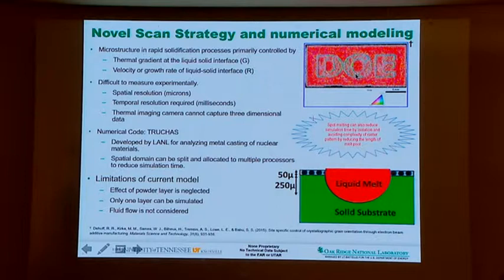So we didn't have an a priori computational model to describe what we want. This was a problem given to Narain. He said, "Suresh, it's too difficult to handle powder and everything, so let me make some assumptions." Since we are only putting down 50 micron, but every time you deposit the electron beam you melt around 250 micron into the depth, he throws away the powder effect for the moment. That's correct, because the powder's thermal diffusivity is very low, so we can ignore that.